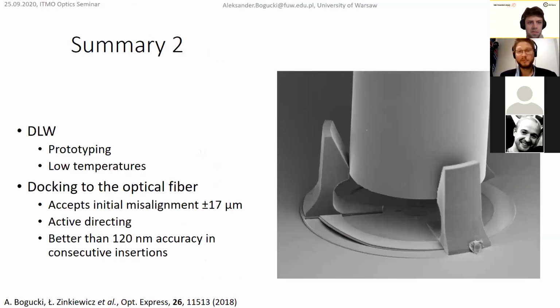Okay, so, summary of this part. It was much faster. Direct laser writing is good for prototyping, because this is an example of prototyping coupling, right? If you are aiming at your final application or final device, then of course you can make some grooves and prepare your substrate in a fancier way, or add technological steps to couple the optical fiber to the structure. However, when you are in a rush or just in a laboratory and you don't have time, then you need to work on your own. And then such prototyping is really nice because you can quite fast change parameters and experiment with them. And it was interesting for us that this resin photopolymer, IP-Dip from Nanoscribe, withstands low cryogenic temperatures pretty well. And we obtained these accuracies here.